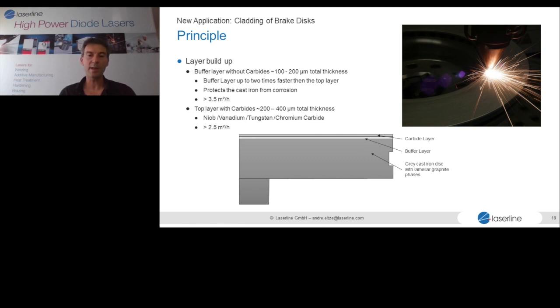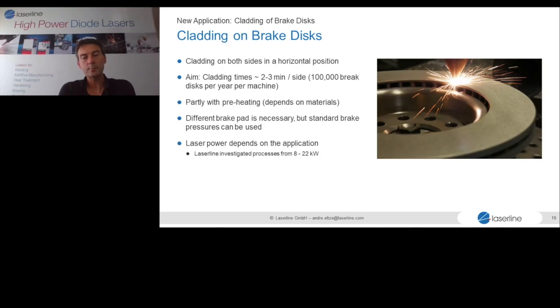Why do you need the buffer layer? The reason is that the carbide layer has tendency to cracks, and then you would get a corrosion problem through the cracks of the carbide layer. This is why you need several layers, and we've done this development together with a car manufacturer and manufacturer of brake discs. And the aim of this project, so this is on standard brake discs for passenger cars in the diameter 300, 350 millimeter. The idea is to get 100,000 of such brake discs per year and per machine.